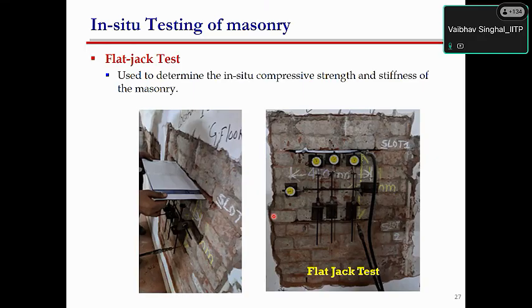So what is done in the flat jack? We cut a slit. We remove the mortar from some part and then insert these plates. The plates you can see here are primarily flat jacks. These are hollow plates where the oil will be pumped inside. You can put two plates, one at the top, one at the bottom, and then apply the pressure. And then you can put some sensors or dial gauges to measure the deformation.